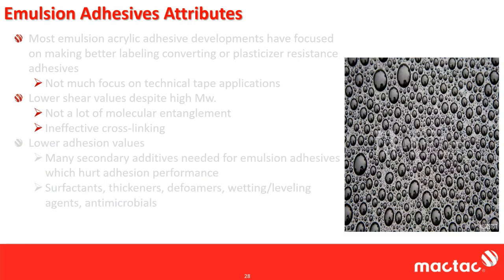And a lot of why you have this is, I've got a graphic over here of what water looks like on a freshly waxed car. You can imagine taking a very polar molecule and putting it onto a very non-polar release liner, a siliconized release liner. It's a lot like taking that same polar molecule of water and putting it on a freshly waxed car. All your water beads up. So you have all these other additives in there really so that you can coat that release liner, because if you didn't, everything would bead up and you wouldn't have a nice cohesive coating, and get yourself a nice looking tape. You would get something like you see on the right, which would have almost no real use as a tape in the pressure sensitive industry. Those would be too thick, you wouldn't be able to dry them, the web would be too inconsistent, you'd never be able to slit through them, things like that.